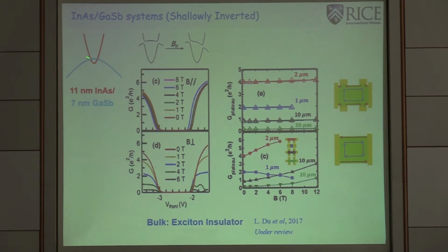Okay. So according to this picture, if you apply a high enough magnetic field, eventually you will turn this quantum spin Hall effect into a semi-metal. So that's one of the criteria used in the reference paper to distinguish whether this is a topological insulator or a regular semiconductor. Because if you have a regular semiconductor and you apply an in-plane magnetic field, basically nothing will happen. Therefore, you can identify that as a semiconductor band structure. But shown here up to 8 Tesla, and also in other experiments we go as high as 20 Tesla, we don't see anything change in terms of the conductivity. Therefore, in this material, there is no such consequence coming from the in-plane magnetic field.